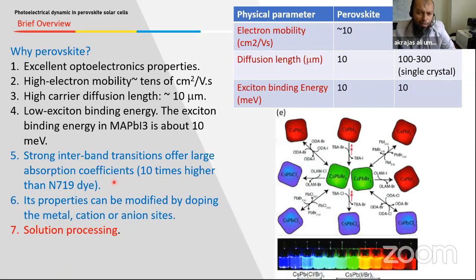Another interesting phenomenon shown by perovskite is that its properties can be simply adjusted by a simple modification of the metal, cation or anion sites. For example, in this picture, the color represents the photoluminescent properties of cesium lead bromide. It can be changed to red or blue when we substitute the bromide anion with iodide, or bromide with chloride. Depending on the concentration of the doping, we can even control the emission wavelength. So we may produce material with desired properties and, of course, desired performance.